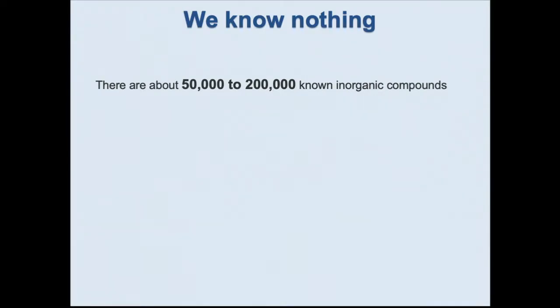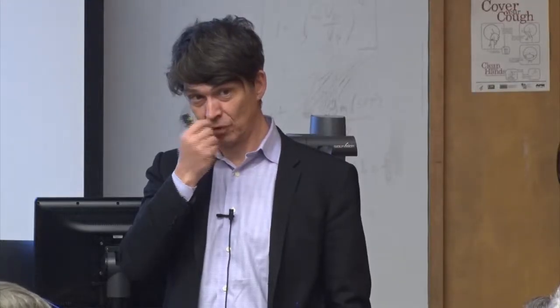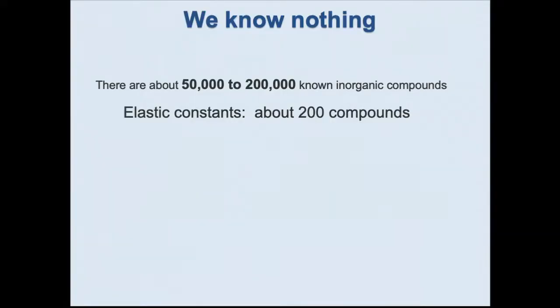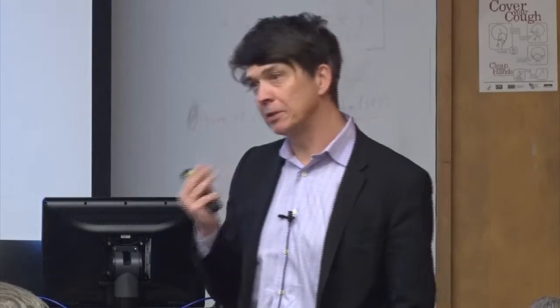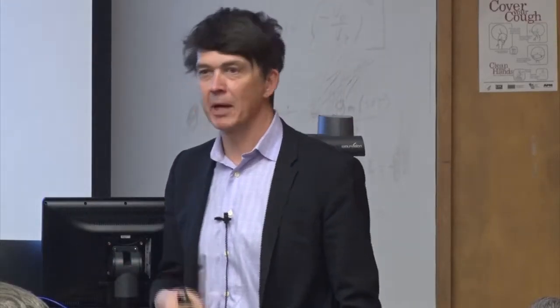So how much do we know about them? It's a good question. We act like we know everything about compounds. Well, if you want to know the elastic constant tensor, 200 compounds. We know a few more bulk moduli and Young's moduli, but actually the full tensor, 200 compounds. And I may be off by 50 or 100, but that makes it 300. The best known property is Tc, because it's been measured over and over again on compounds. It's pretty easy to measure. So Tc, the superconducting transition temperature, is known for about 1,000 compounds.